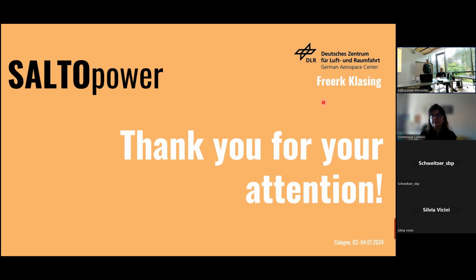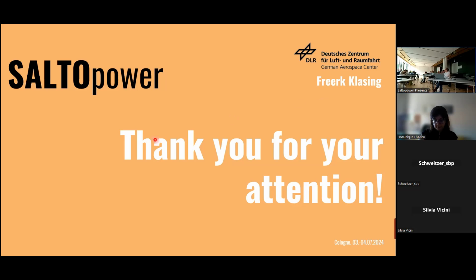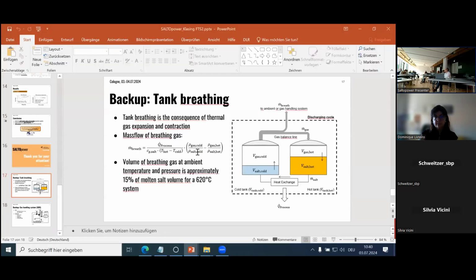Maybe I can add one comment, because there's always a lot of confusion with the gases because it depends on the salt. That's true for solar salt. But if you work, for example, with Hitec salt, which contains a lot of nitrite, you don't want maybe to have the oxygen, because oxygen will go into the salt and change the salt. So it depends on the salt, but for solar salt, it's beneficial. Yes, it's beneficial to have oxygen to stabilize the salt.